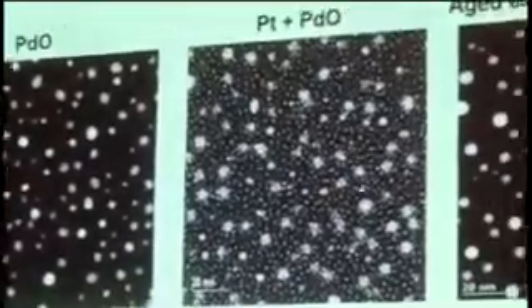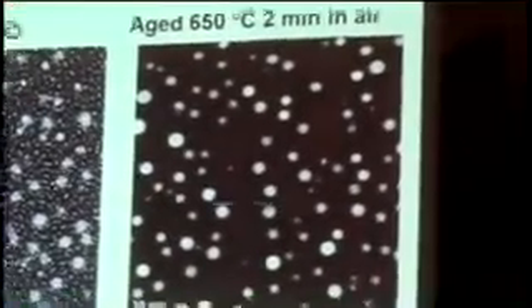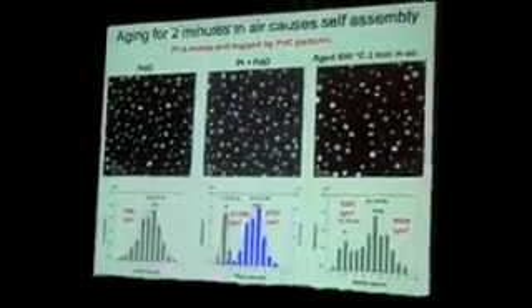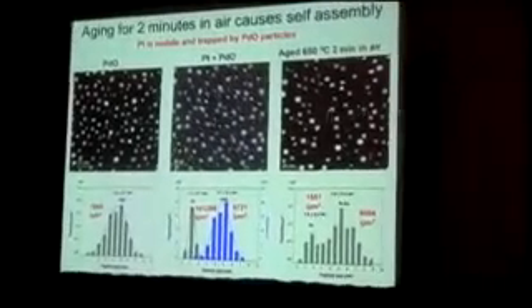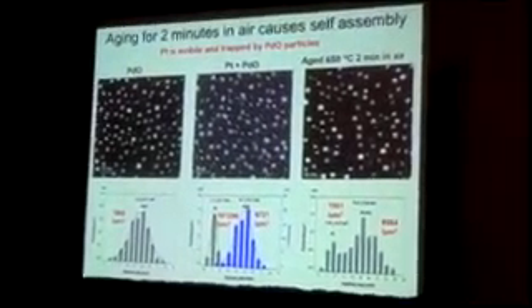XPS confirms, yes, we have palladium oxide. What next? We heat it up for 2 minutes. That's 650 C. So same sample, heat it to 650 C, and miraculously, all those platinum particles go. They disappeared, and what has happened is the platinum has migrated and converted the palladium oxide into metallic palladium in air, in flowing air.